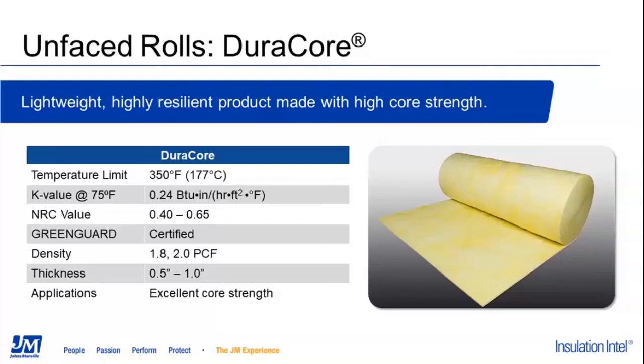So DuraCore has the same temperature limit of 350 degrees, a thermal value of 0.24, NRC values between 40 and 65. It is GreenGuard certified. Densities available in 1.8 or 2 pound, and in thicknesses from 1/2 inch to 1 inch. DuraCore also has the high post-consumer recycled content at 56%.